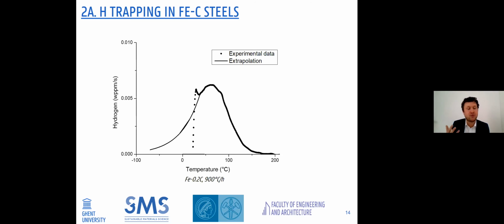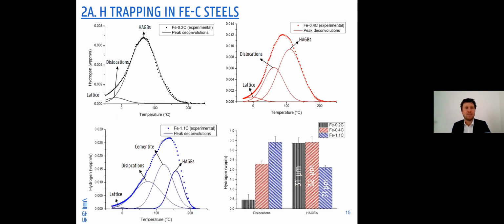As you can imagine, deconvoluting such a spectrum which shows this high jump is quite challenging and quite complex. So this is why we extrapolate the peak. We know that we have 1 minute in between charging and testing, so we know how much hydrogen is lost during the 60 seconds in between charging and testing. And then the experimental data is further treated by an exponential extrapolation towards lower temperatures, as can be seen in this graph. This is done by taking into account the content of hydrogen that was lost in between charging and testing. And this resembles very weakly trapped hydrogen linked to interstitial hydrogen. So then we have treated our data and we can do deconvolution.